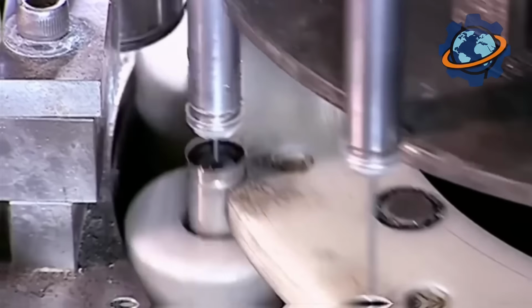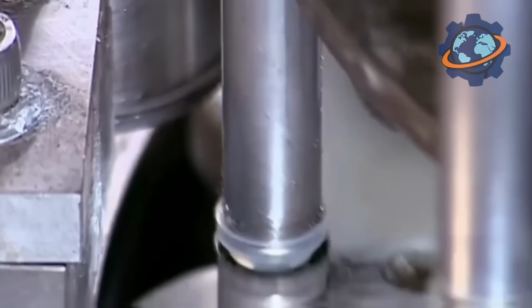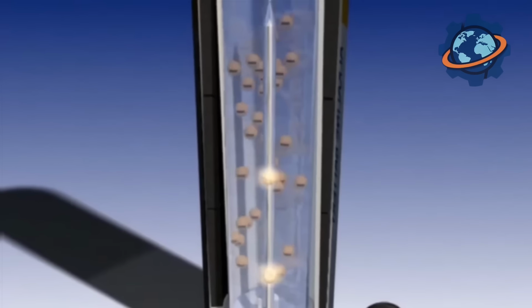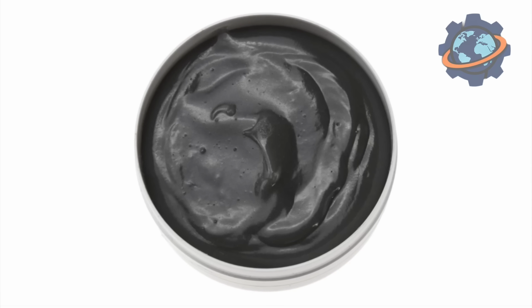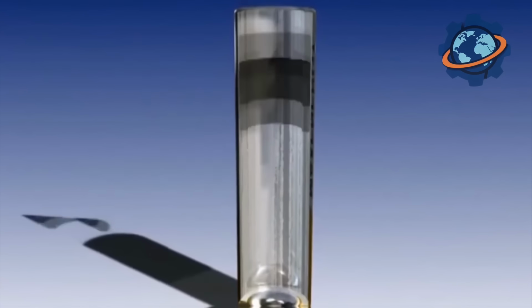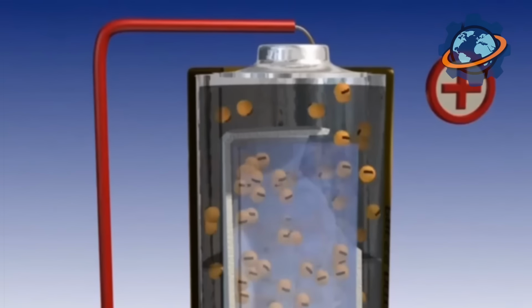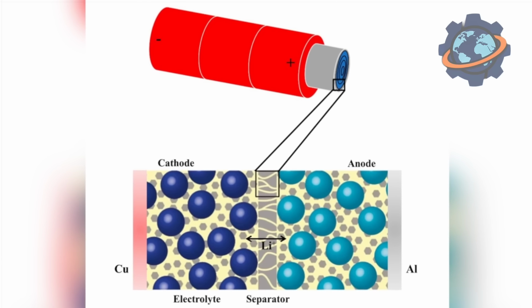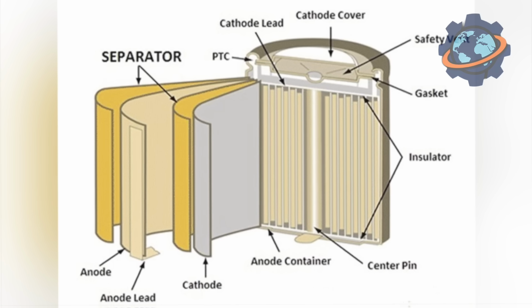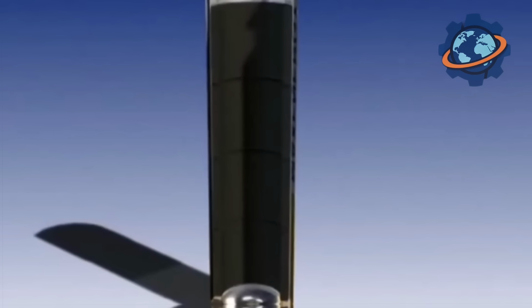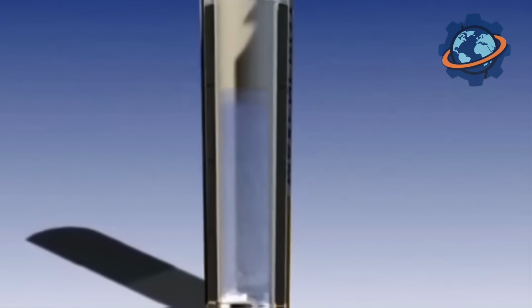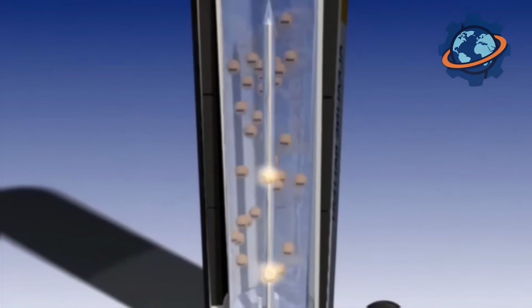It looks like a dark gray mass that is compacted by presses into a solid crust. It needs to be dense, but not too dry, so that current can flow, but without the risk of leakage. Each battery contains about 8 grams of this paste, and the compaction density is precisely controlled to tenths of a gram. Next, the separator, a thin layer that prevents the cathode and anode from touching each other to avoid a short circuit. This is an extremely thin polymer membrane, less than 1/100th of an inch thick. But despite its thinness, it's strong and porous. It allows ions to migrate, but keeps the masses separate.